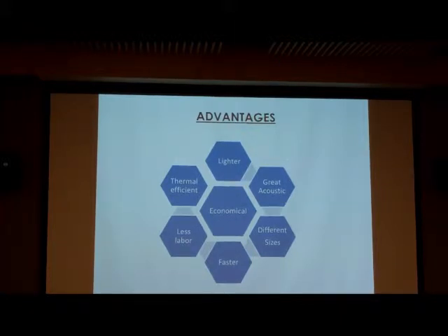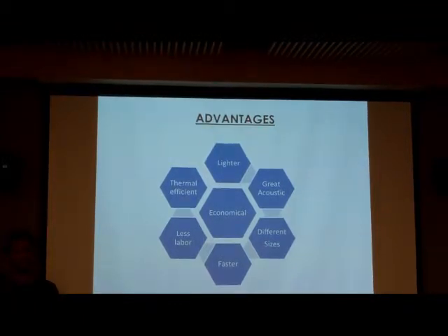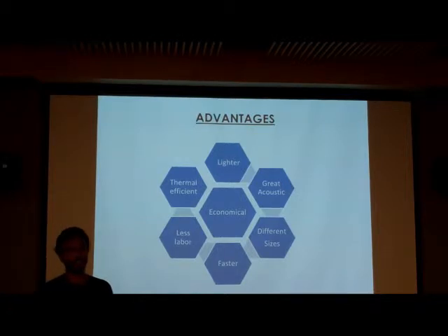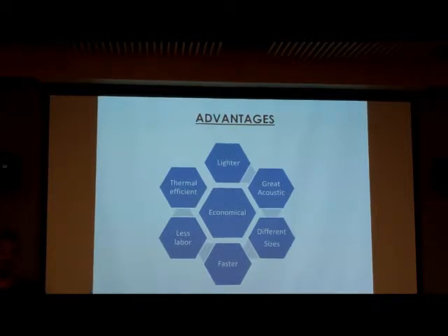So the faster the construction, the more advantages we can make use of. It also reduces the weight of the total structure, so we can reduce 27% of the steel and 20% of cement. The larger blocks help us reduce the joints to one-third, so less mortar, and 66% of mortar can be saved.